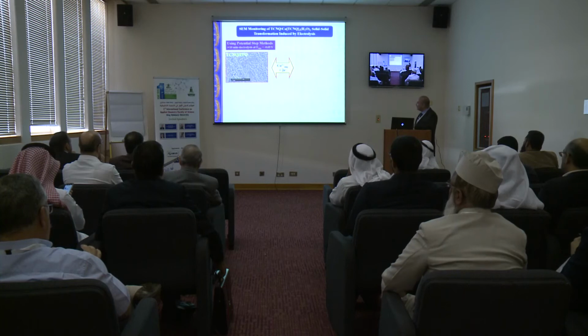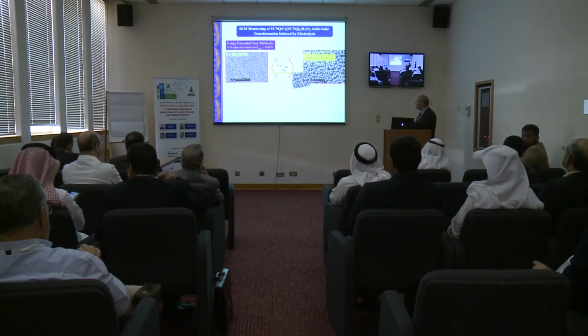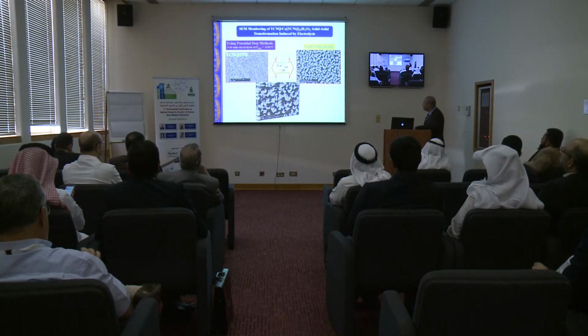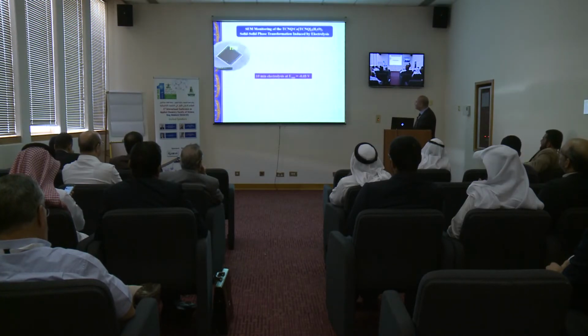An interesting one here is, instead of applying cycling potential, what we do is depositing potential. So what we do is we're holding the potential at this value for 10 minutes, and then we take the electrode out and trying to look at it under the electron microscope. So you can see now that this amorphous material is giving us this kind of pattern where we have this kind of nano or microstructures and all having outgrowth from the crystal.